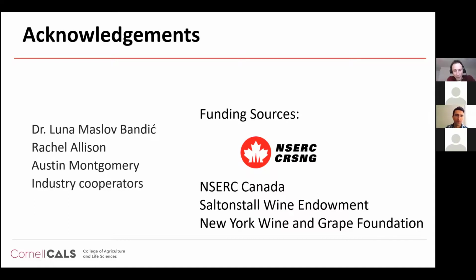Casey, can you touch on low pH wines? Could acidity alone cause issues as a result of SO2 interaction? Thank you. Low pH, I think, is an exacerbating factor, but keep in mind, Coca-Cola, pH 2.4, and it uses a thinner liner than wine, and it doesn't have any problems. This is not just a pH only issue. It is also not an acid only issue. We can store wines that have no SO2 in them and not have any problems. The problem seems to be a combination of pH and SO2. And if you don't have the SO2 present, you don't have those pH issues. You can put plenty of low pH products like carbonated sodas into a can with no problems.